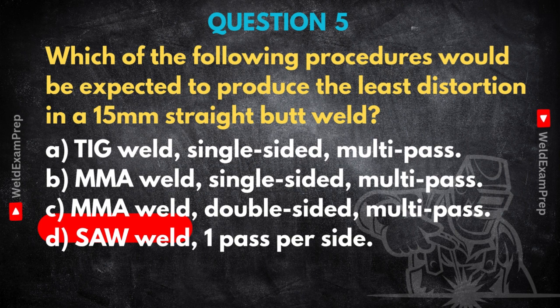Because SAW, with its high deposition rate and deep penetration, can often complete the weld in just one pass from each side. While the total heat might be high, it's applied relatively quickly and, crucially, balanced across the thickness, one pass each side. This minimizes the number of thermal cycles dramatically. Fewer cycles, less cumulative stress buildup. Precisely, and the heat is distributed more uniformly through the thickness compared to many small localized passes. This leads to more balanced shrinkage and therefore less overall distortion, especially angular distortion in thicker sections.